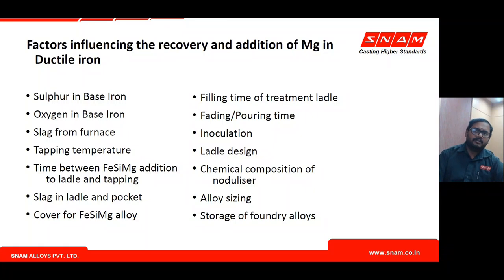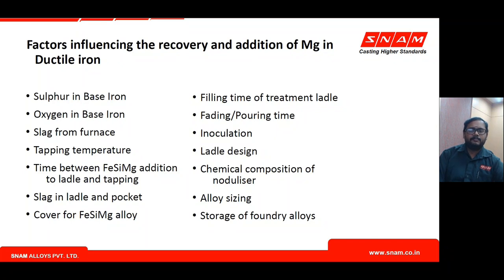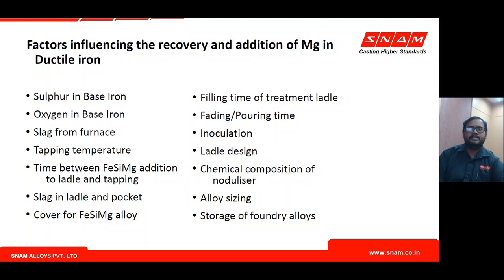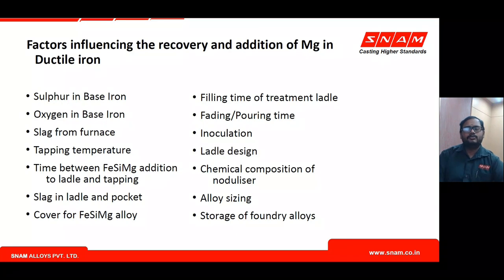If magnesium recovery varies, the required magnesium content in the alloy and addition rate will vary. Alloy addition timing to the ladle matters: if added too early before tapping, the alloy preheats and dissolves faster in the hot ladle. The alloy should be added to the pocket just before tapping. Ladle and pocket cleanliness is critical — slag in the ladle reduces useful pocket volume and reacts with magnesium to generate magnesium oxide or magnesium sulfide, causing losses. Using a cover over the alloy delays the reaction, increasing recovery.